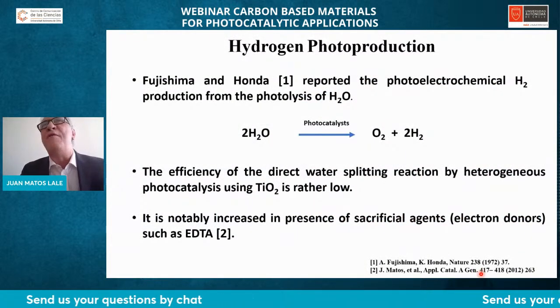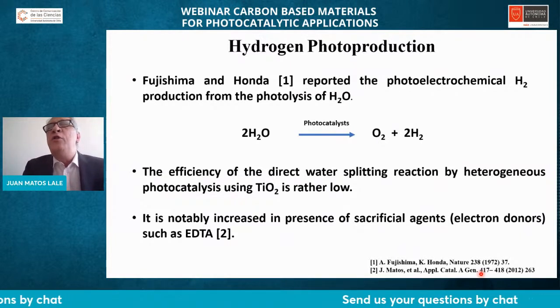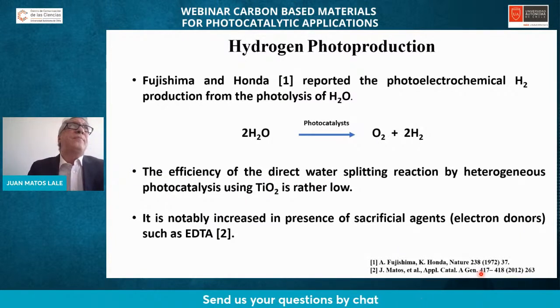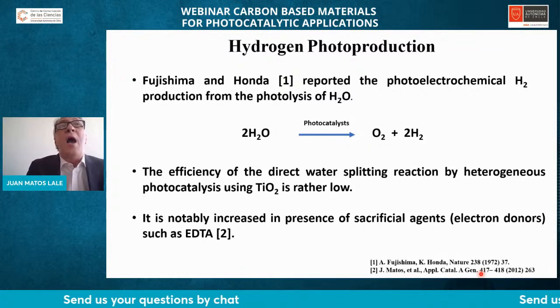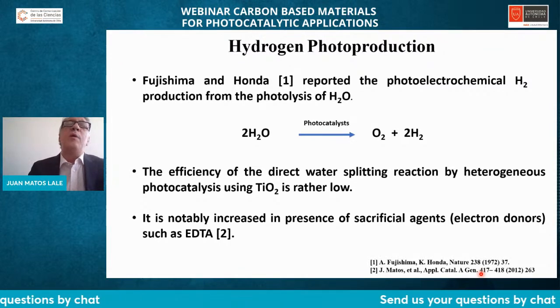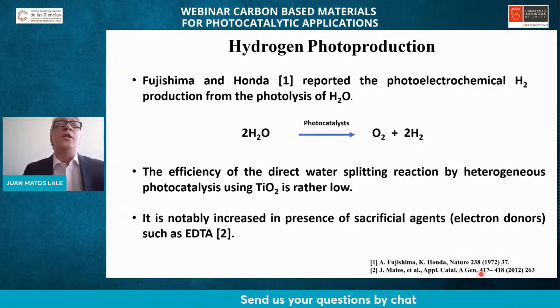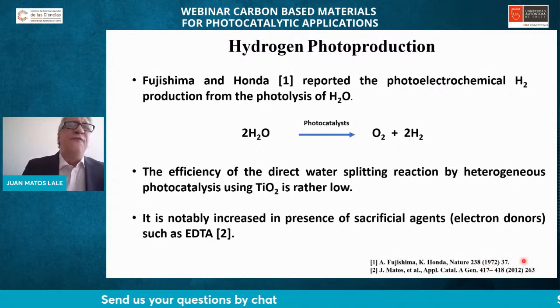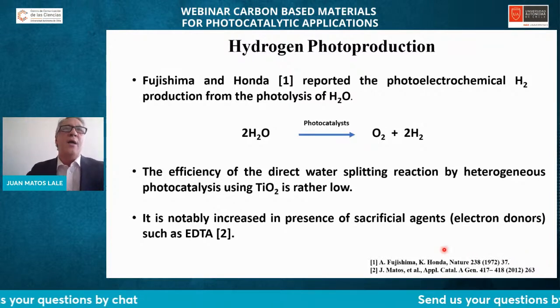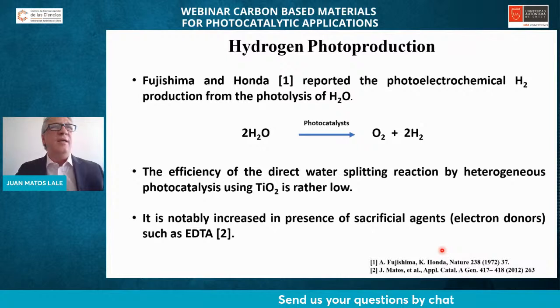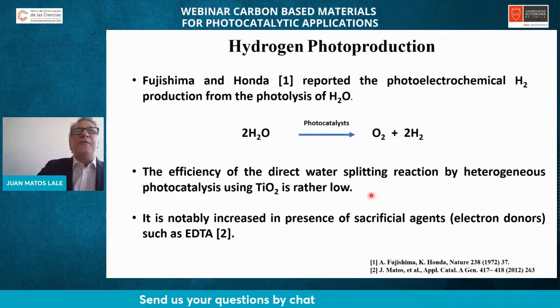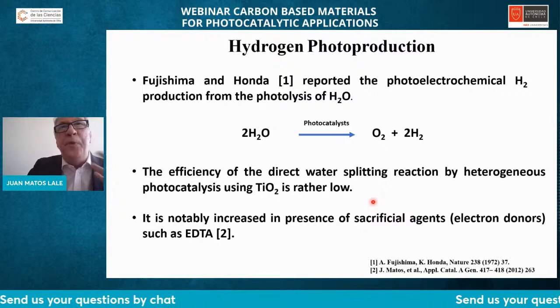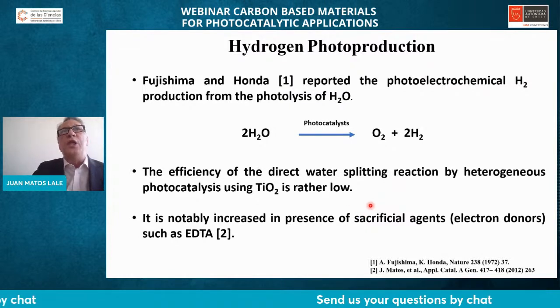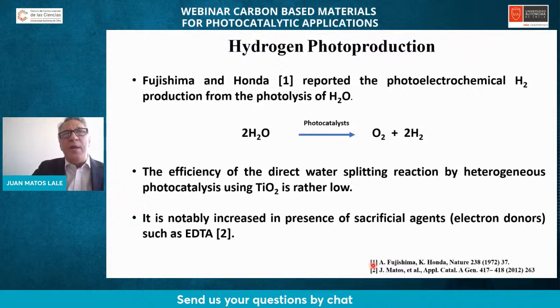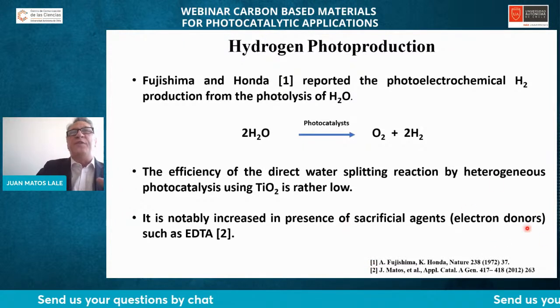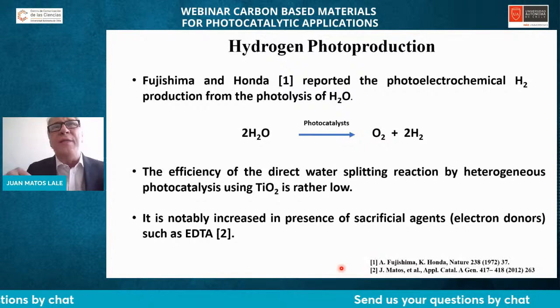What's going on with the hydrogen photoproduction? This is not a new reaction. I like when people talk about green hydrogen, but I always, with great respect, try to say that this is not a new reaction. It was published 50 years ago by Fujishima and Honda. The reason it was forgotten is because the efficiency of titanium dioxide is very poor under solar irradiation conditions. But it can be notably increased by using different kinds of sacrificial agents and, at the same time, by using co-additives to the catalyst.